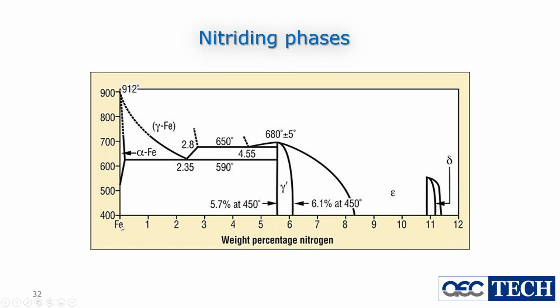So the left side, when you see Fe, is 100% iron, and then 1%, 2%, 3%. At around 6%, we have a phase at between 400 to 600 degrees C. We have a phase called gamma prime, which is the phase that we want. It has the right amount of nitrogen in it, which has a good combination of hardness and toughness. If you put more nitrogen into the environment, you're going to end up with epsilon phase, which is about 10% nitrogen, and it's brittle because it's too hard.